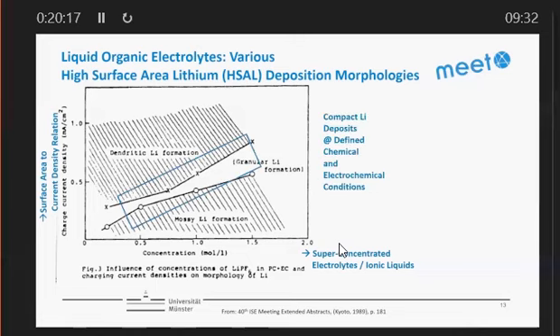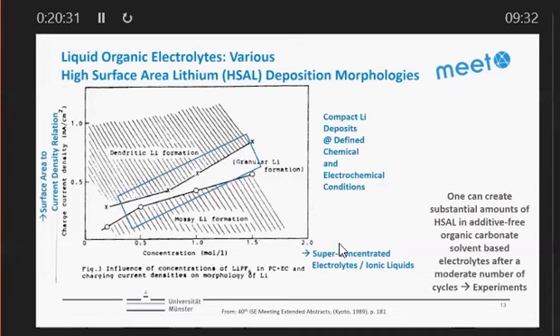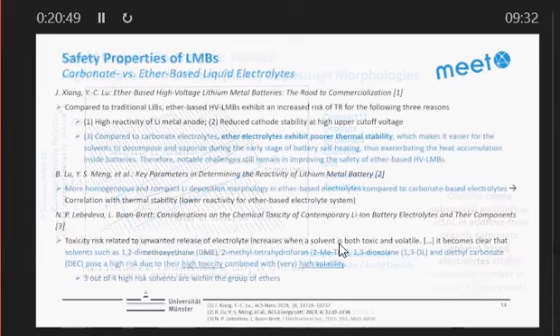And basically, there's a very small range of electrochemical and chemical conditions where this compact morphology happens. So you have to be very careful with what you are doing during cell assembly, but also during cell operation. For us, this is extremely important because we don't want to do thousands of cycles in excellent electrolytes. We want to create dendrites very fast, because then we can look at the impact of dendritic, high surface area lithium on safety. So we use organic carbonate-based electrolytes because then we can harvest dendrites fast.